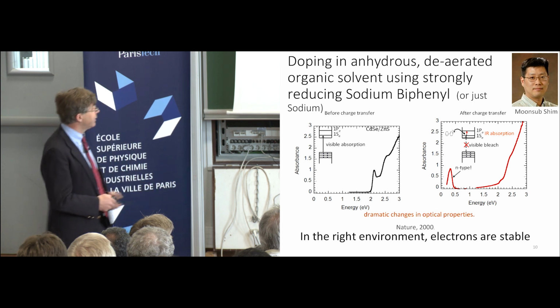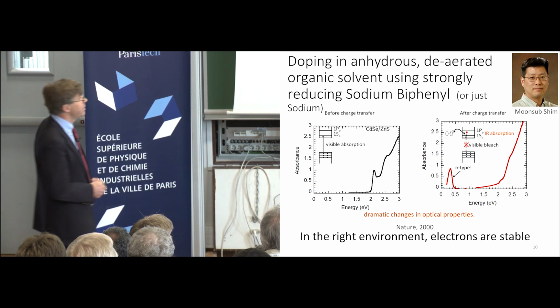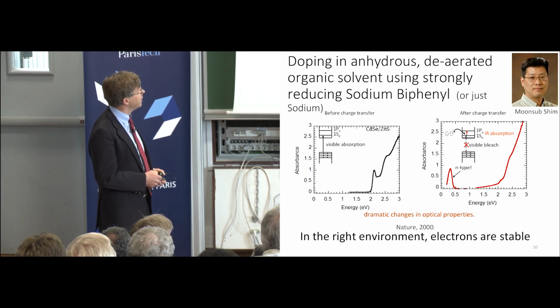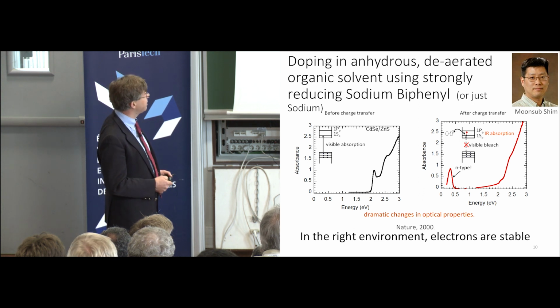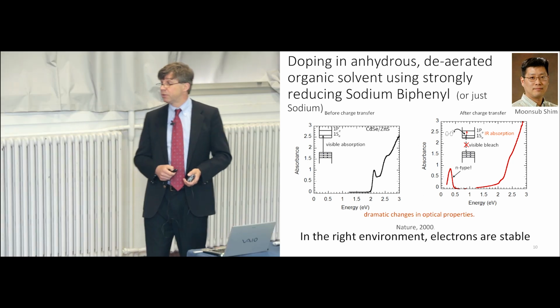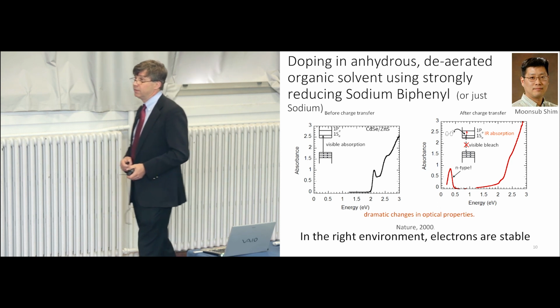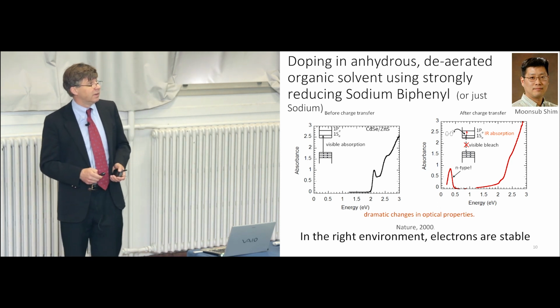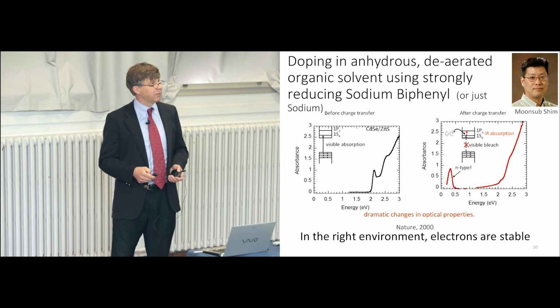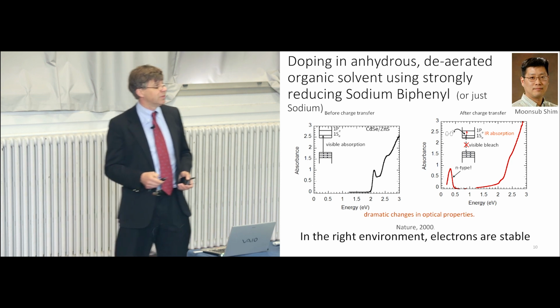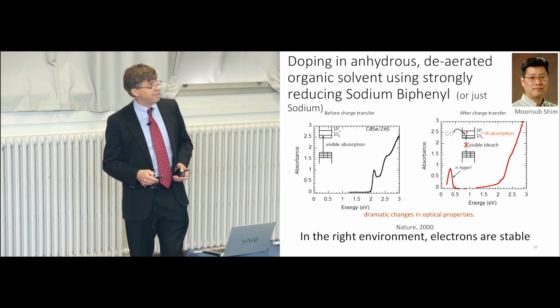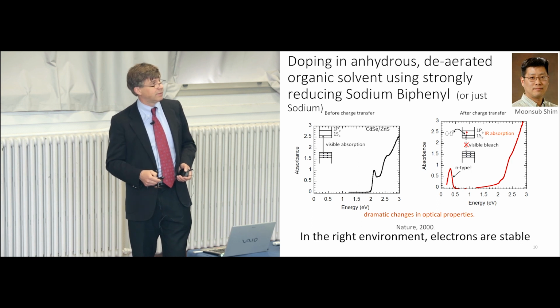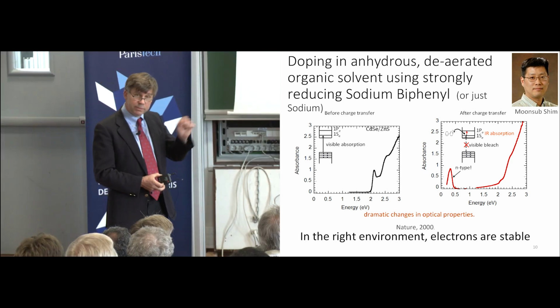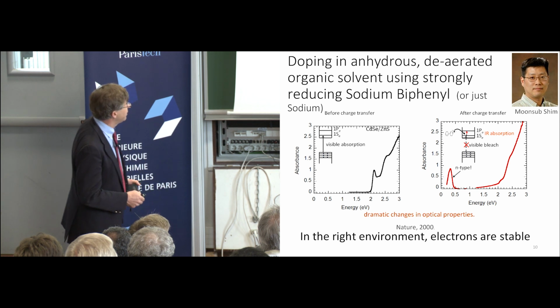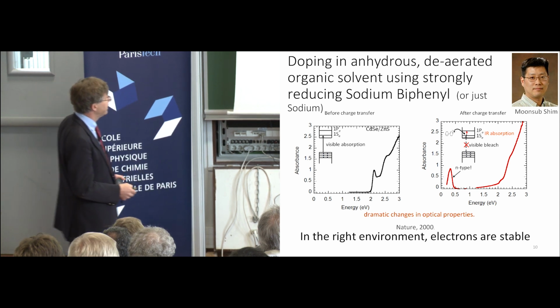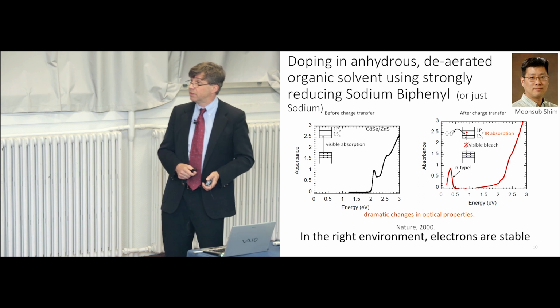And yes, the fluorescence decreased when we made negative quantum dots, but what we found was what we expected, which is that because the system becomes transparent at the lasing wavelength, the gain is in fact higher. Songjun Wang found, and I was not there when he found that, in the middle of the night, that the quantum dot had this threshold, and just by switching the potential a little bit, just to make the dot transparent at the emission wavelength, the threshold was reduced by a significant amount.